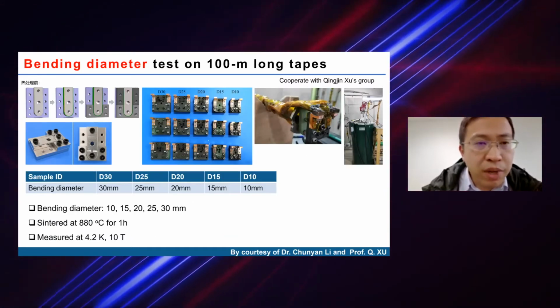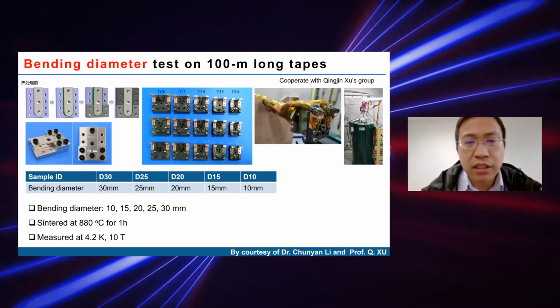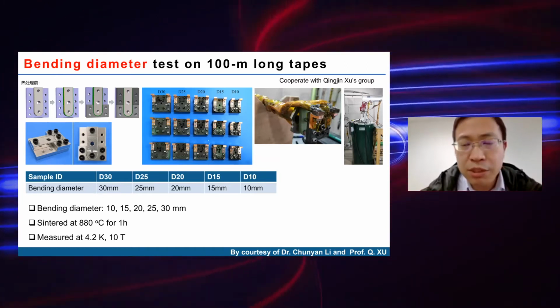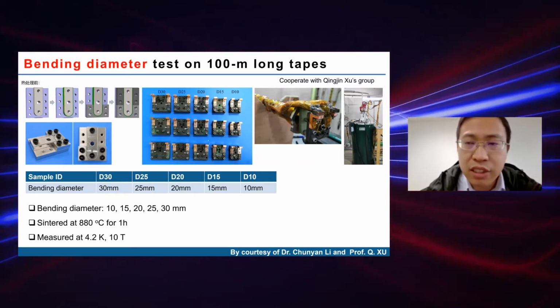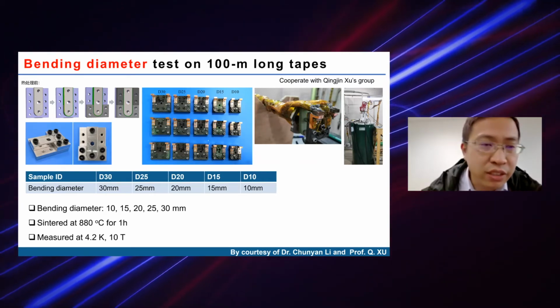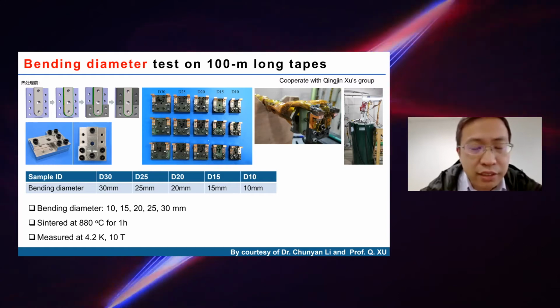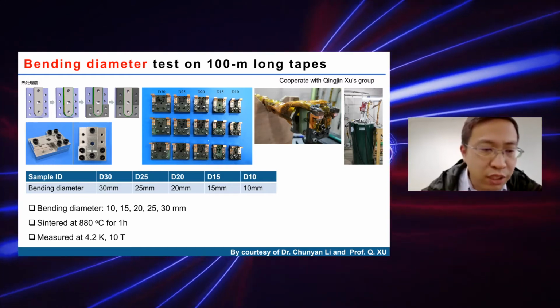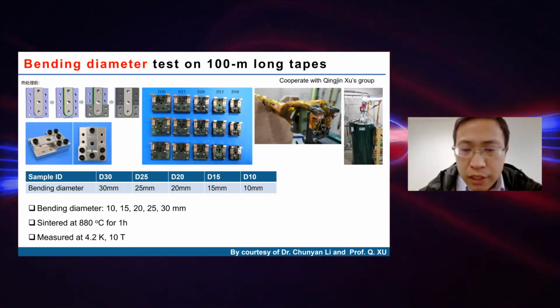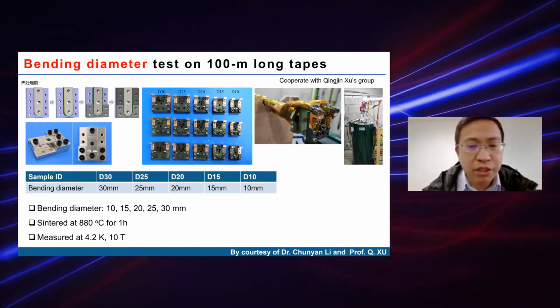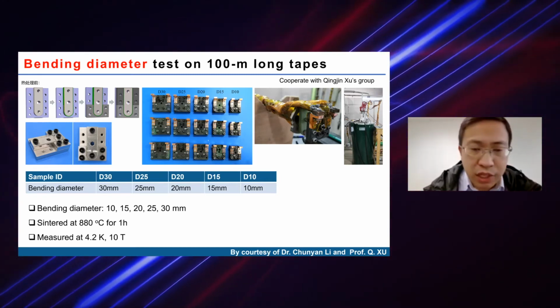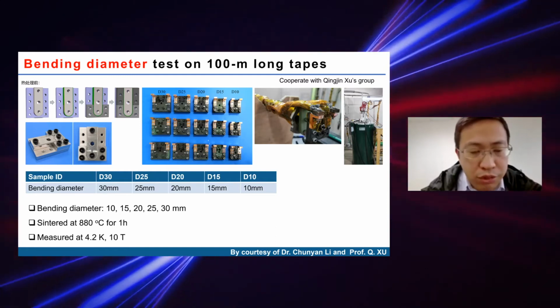Then we performed a bending diameter test on our 100 meter long tapes. It's a 7-filament tape, and we fabricated these special devices with different bending diameters from 10 millimeters to 30 millimeters. And we test their Ic at 4.2 Kelvin and 10 Tesla.